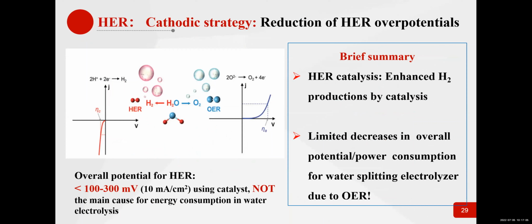So let's have a very brief summary about HER strategies as the cathode. So we can enhance hydrogen production by using suitable catalysis. However, you can see that the overpotential for the HER is relatively low. For example, about several tens or several hundreds millivolt. This overpotential is not very high, and actually, the OER overpotential is much higher. So even if you can lower the overpotential of HER, there will be less contribution to the energy consumption reduction.